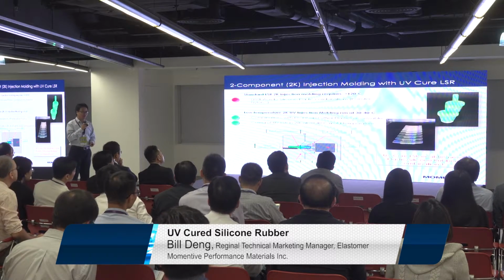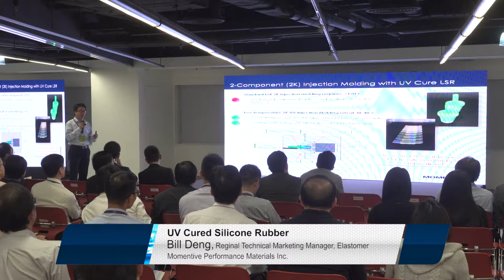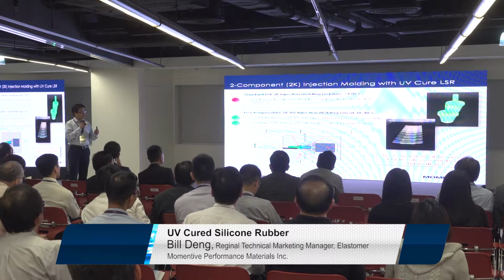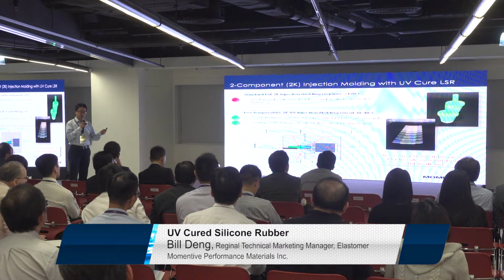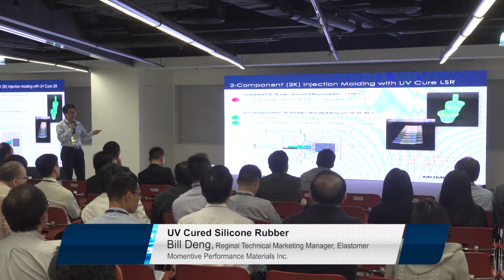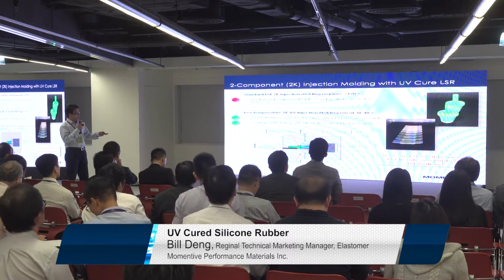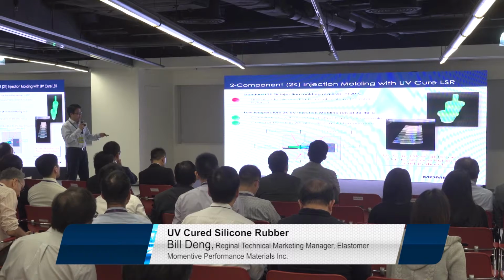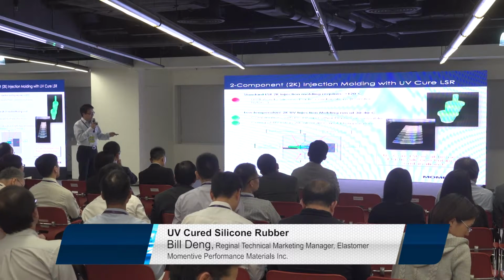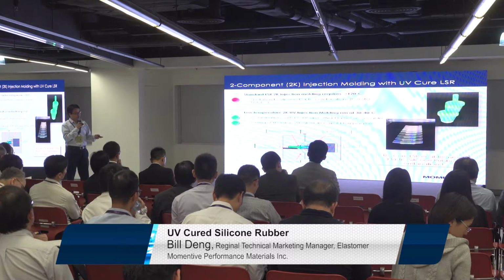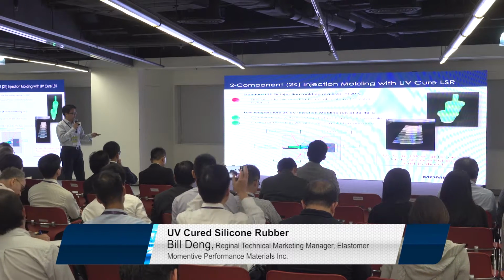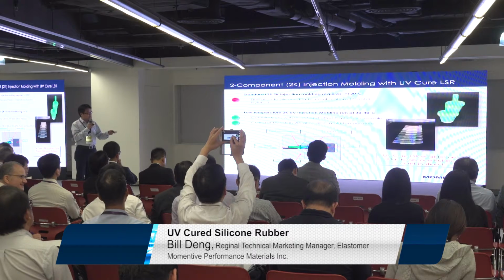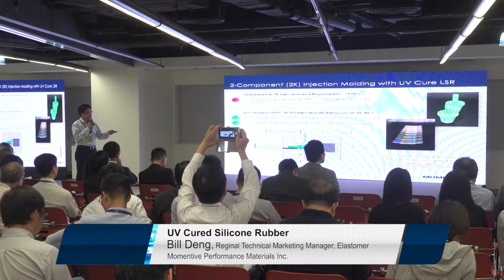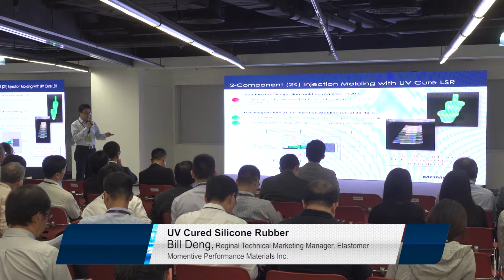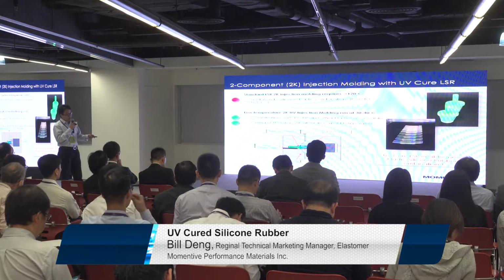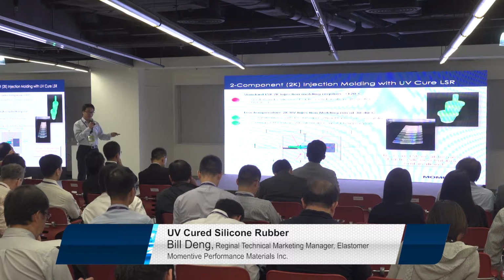The PP melting point is very low. You cannot use traditional silicone rubber to bond with this plastic, because if you apply heat, the plastic will be destroyed. And here is something we use for a soap case. The plastic is also PP, and PE can also be used, and the same issue happens. So that's why we use UV cured silicone rubber to bond with low melting temperature plastic to make the part.